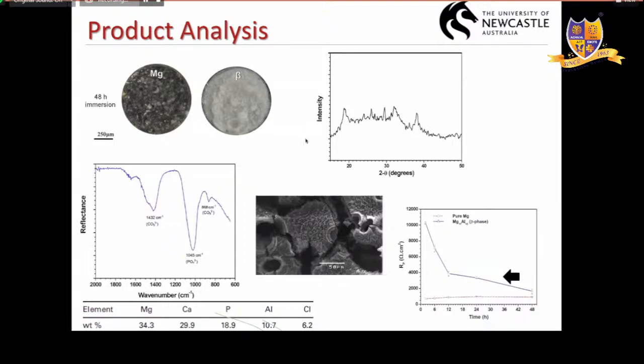But we took that sample and separately analyzed how it behaves over time in body fluid, and surprisingly, it's good news that although the resistance of this beta phase at the initial stage was quite high, while the base metal, pure metal, dissolution is fast, it started to decrease over a period of time, which suggests that these beta phases are not highly stable. It dissolves over time, although more slowly than magnesium. Otherwise, we can't use this material for implant applications.